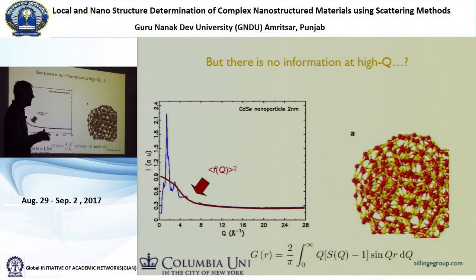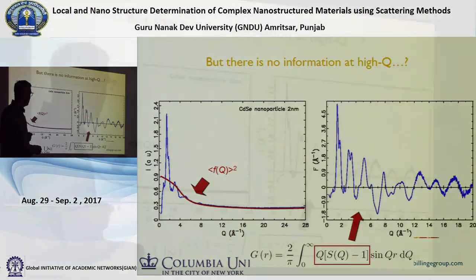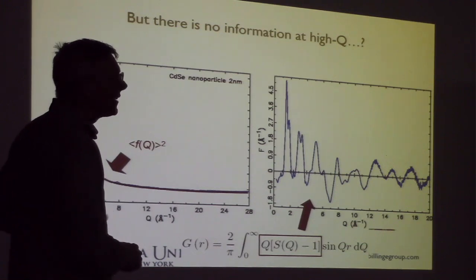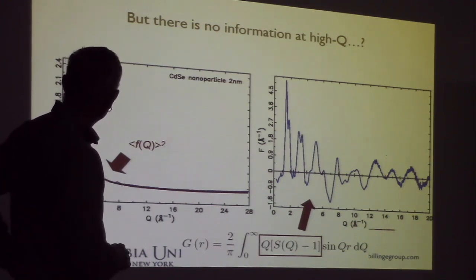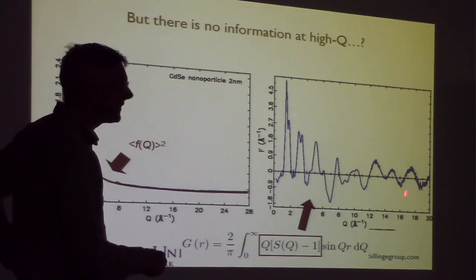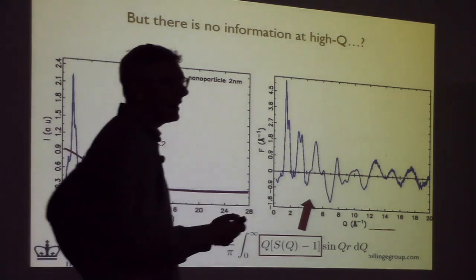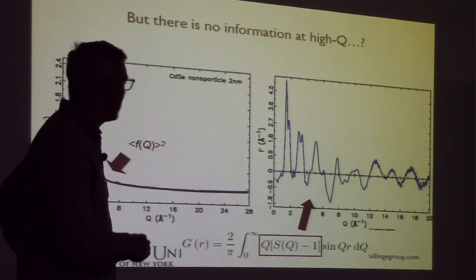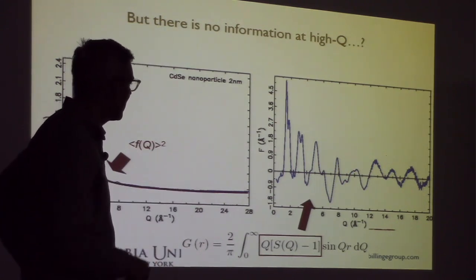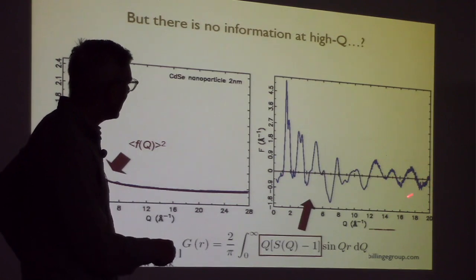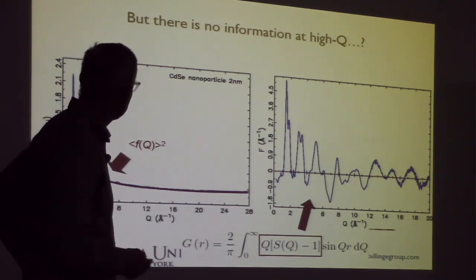Now, if you divide two large numbers by each other, even if the numbers are different by a little bit, you get a large enhancement in signal. So when we do this division, we get this curve. So this curve is the same as that one after we've done the normalization. And so this peak here is that one, and this peak here is that one. What you can see is out here where there was no intensity, there's actually quite rich intensity there. You just have to apply this correct normalization to get it. And now we have much more information that we can use to do a structure determination. And you can see that the signal actually went out further. We just stopped it.